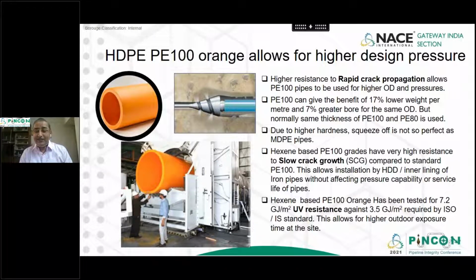Latest generation hexene-based PE100 grades have very high resistance to slow crack growth, called SCG, compared to standard PE100. This allows installation by horizontal directional drilling or inner lining of iron pipes without affecting pressure capability or service life of pipes. We have also tested hexene-based PE100 orange for up to 7.2 gigajoule per meter square UV resistance, which is normally specified for 3LPE coating, which is black. Typically in the pipe industry, the requirement is 3.5 gigajoule per meter square, which is required by ISO and IS standards.